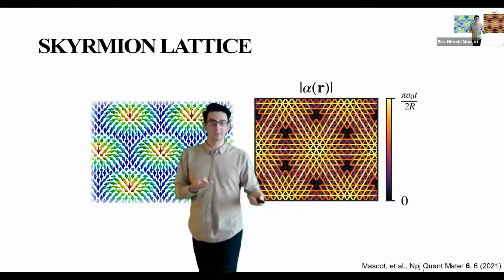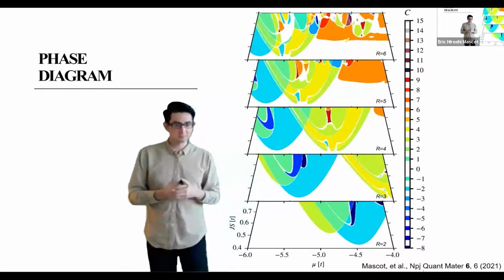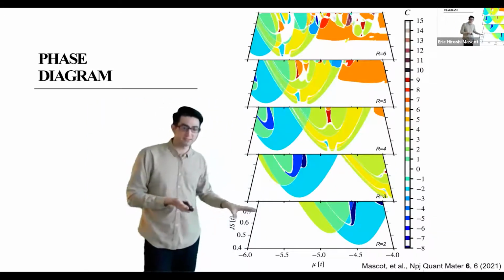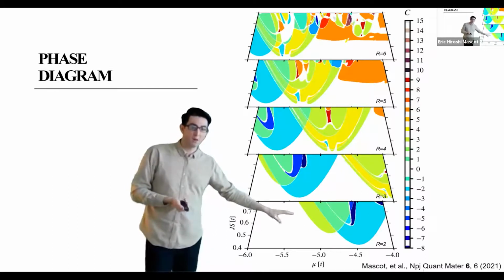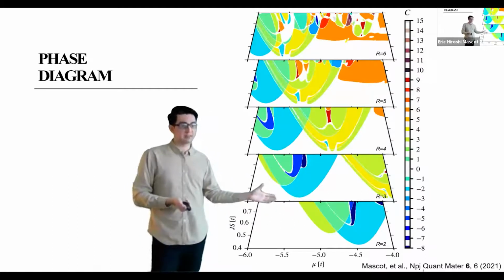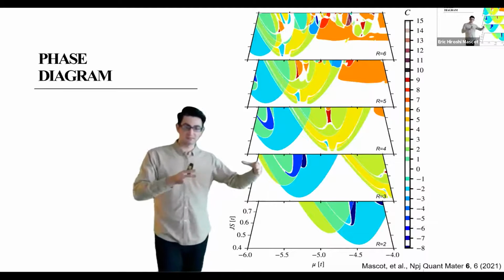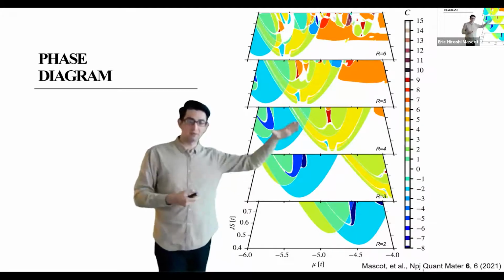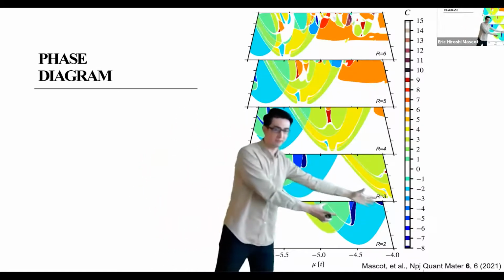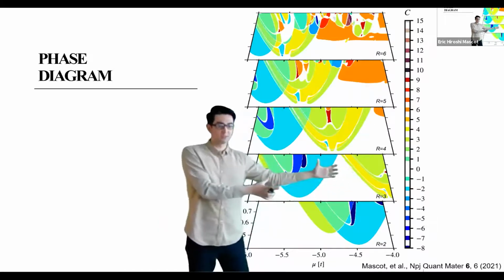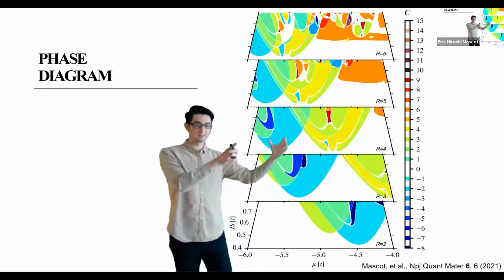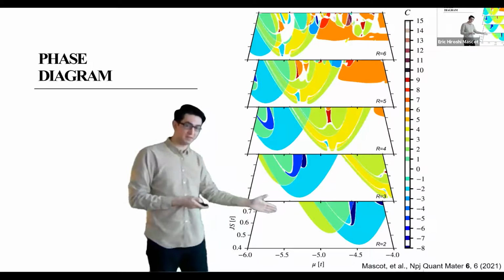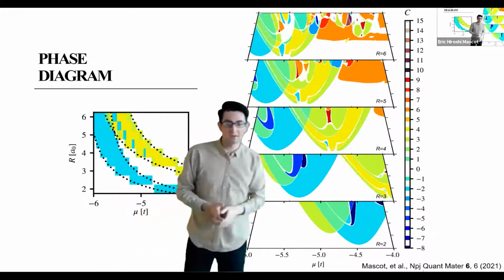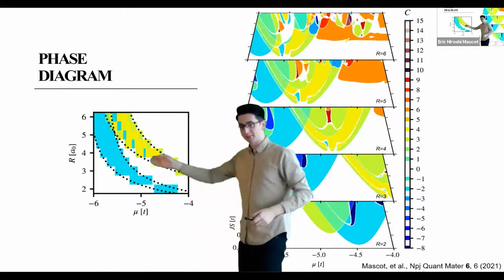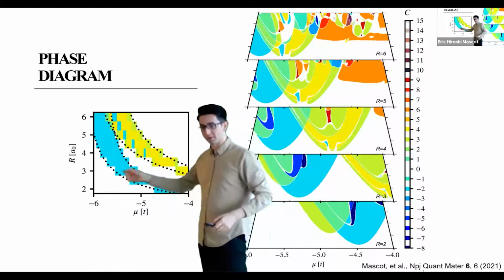So we calculated the phase diagram for this. Again, we have our magnetic exchange and the chemical potential. But as we change the size of that lattice, making the individual skyrmions bigger and bigger, what we see is that the phase diagram shifts over to the left. And if we look at a specific cut, we can look at how the critical line shifts, and this goes as 1 over r squared.